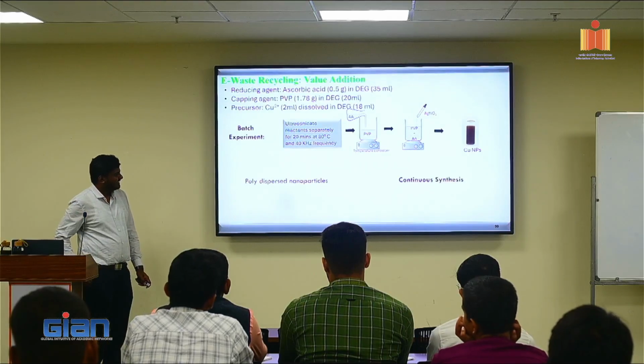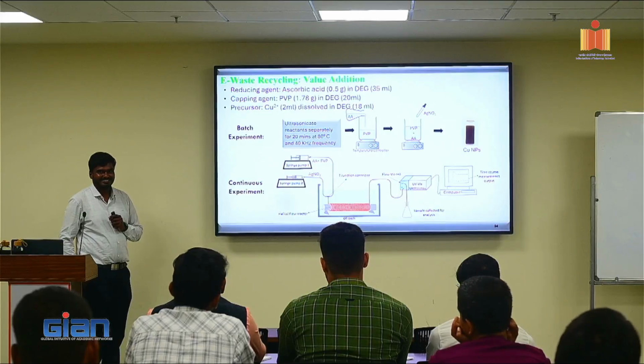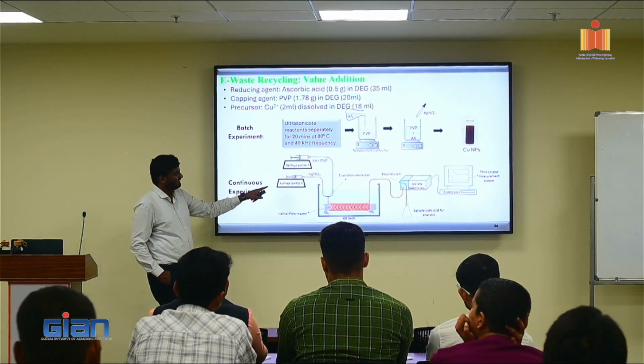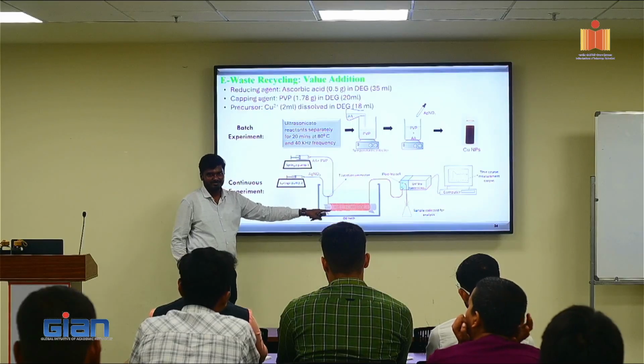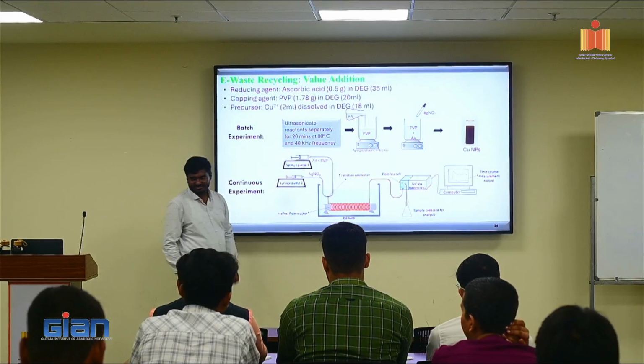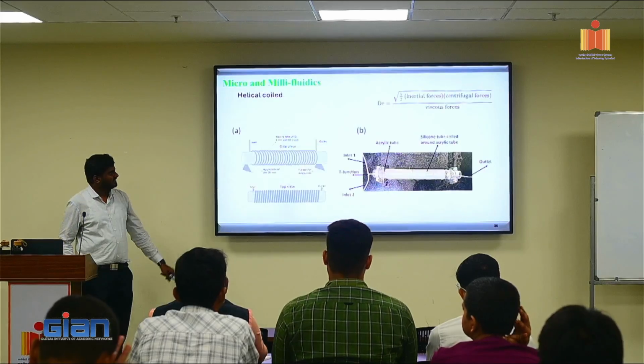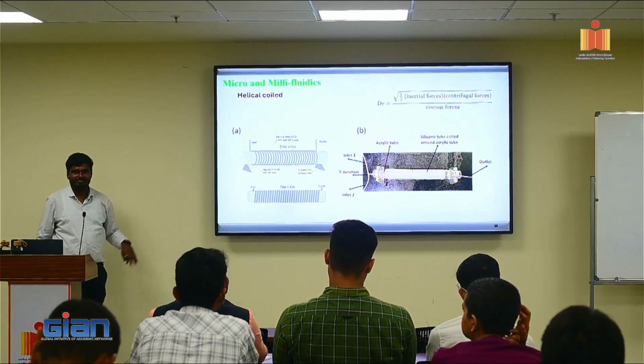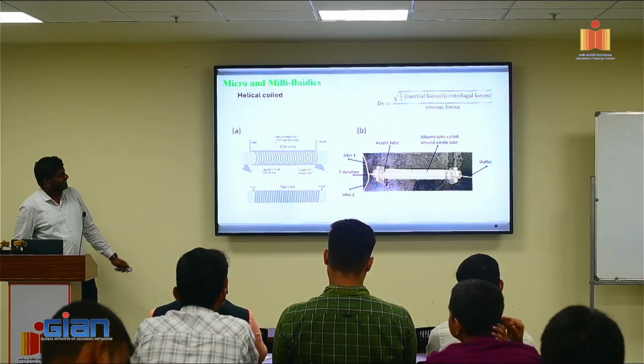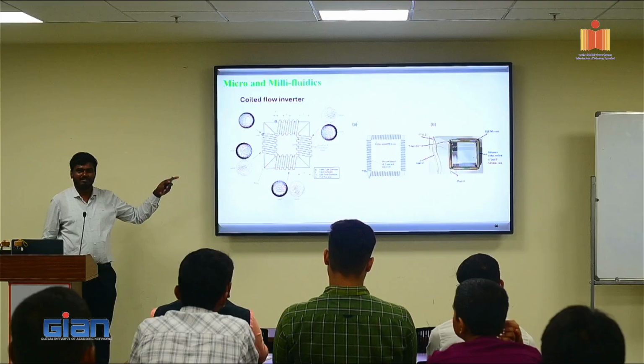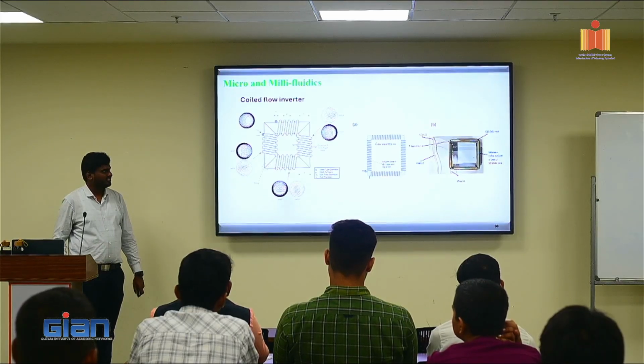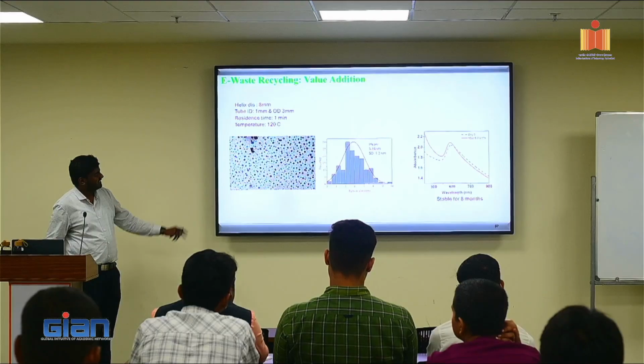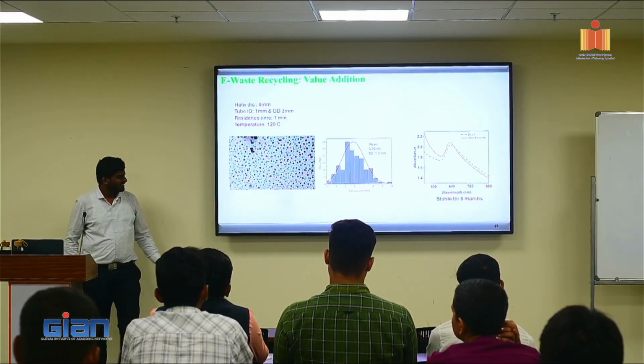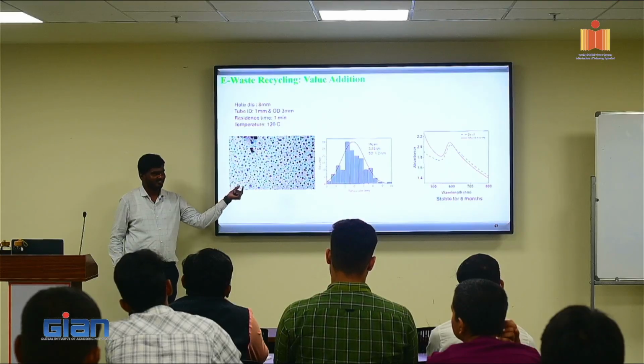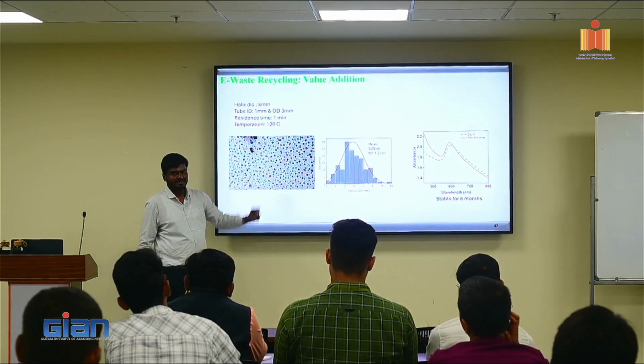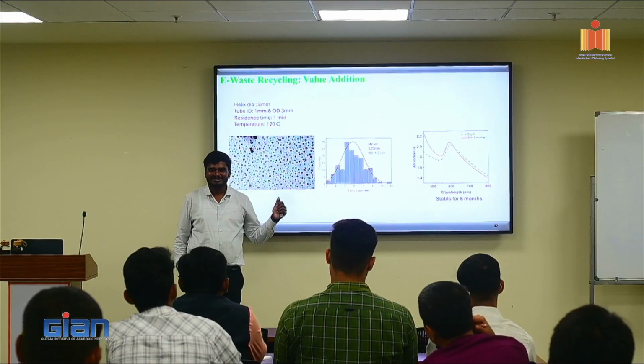Then what we did later was, we thought, can we go with continuous synthesis? So rather than adding batch-wise, we were continuously pumping into different types of reactors, continuously monitoring, and we synthesize nanoparticles in this. So basically these are some of the flow reactors that I developed in IIT Madras. And then we modified this to get much more precisely size-distributed nanoparticles, and eventually these are the nanoparticles that we got. You can see that this is a scale of 20 nanometers. The size is approximately 6 nanometers, and this has a huge market value.